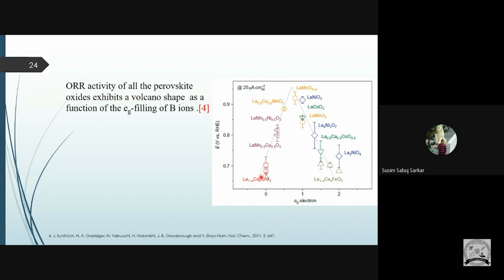First of all, chromium 3 plus has no Eg electron, because its configuration is t2g3. Chromium 2 plus is t2g3 Eg1. That means chromium can go between 2 plus and 3 plus for performing this catalytic activity, but generally chromium is placed in the plus 3 oxidation state, and in that case the Eg occupancy is 0 and we can't get much activity.